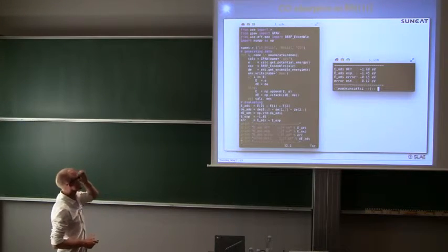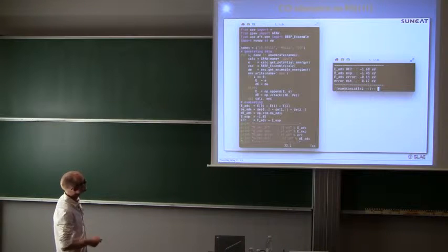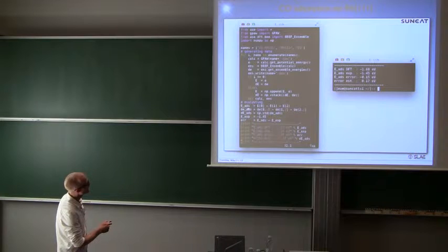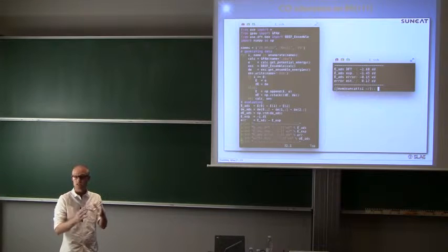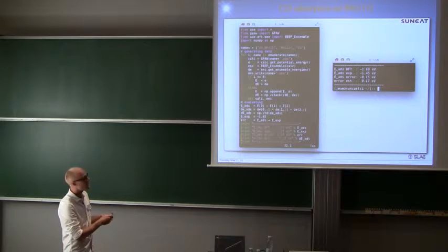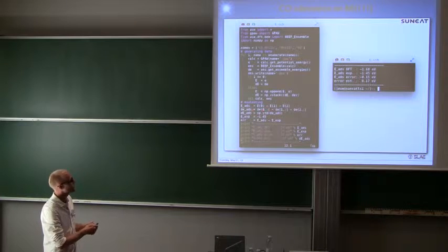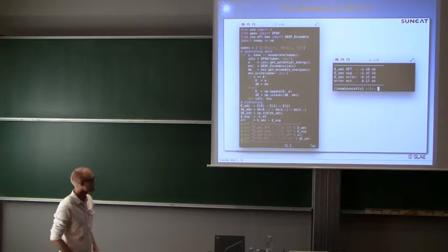This is just a quick example of how I actually do it. Here I'm looking at adsorption of CO on rhodium 111, and I go through a loop over different GPAW files. Here I'm calculating the adsorption energy. Here I'm calculating 2,000 different predictions of the adsorption energy, and I define the error estimate as the standard deviation over those predictions. The predictions follow a Gaussian, which is centered at the actual adsorption energy. So whether you take the standard deviation or the root mean squared deviation, it's going to be the same.